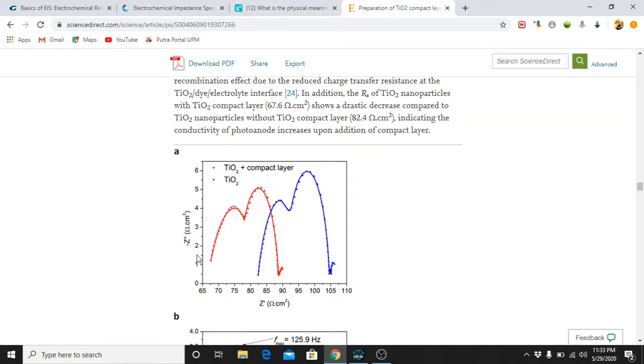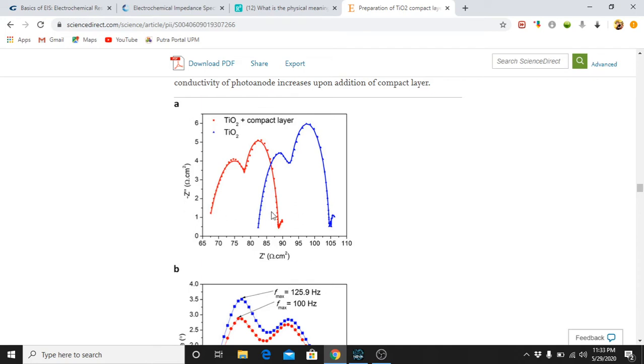In a solar cell, we are using EIS, electrochemical impedance spectroscopy, to measure the charge transfer resistance between the interfaces. Because in the dye-sensitized solar cell, we normally have three interfaces, but from the graph here, you can see two interfaces. At high frequency, this is the counter electrode electrolyte interface, and at low frequency is the TiO2 dye electrolyte interface. It depends on the system. If it's about a supercapacitor, the interface is quite different.